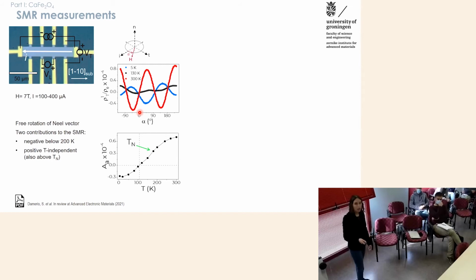from an antiferromagnet. But upon increasing the temperature, this modulation first decreases in amplitude and then it reverses its sign. So at a larger temperature, we observe what is more similar to a ferromagnet or a paramagnet. Here you can see a plot of the amplitude as a function of temperature. And what was surprising for us is that this change of sign was not occurring at the Néel temperature where the material becomes paramagnetic, but actually was occurring much lower, at around 100K.